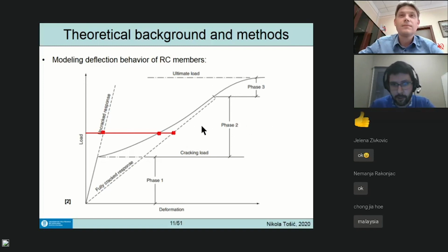But in service, you're going to be here in phase 2, or even more problematic for slabs in buildings, in service you're going to be actually very close to the cracking load. So this will cause an additional large uncertainty, because if you are slightly under your cracking load, this is your deflection, but a bit above, the deflection is twice as large, 3 times as large.